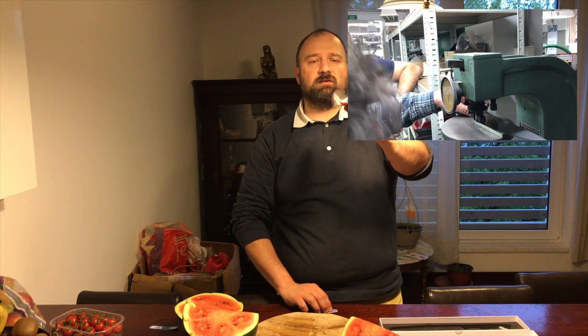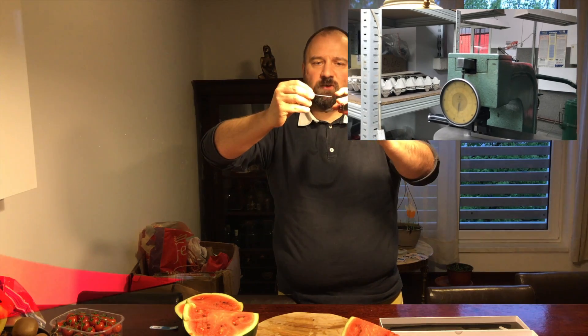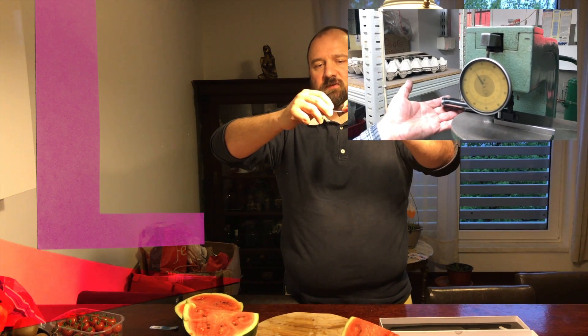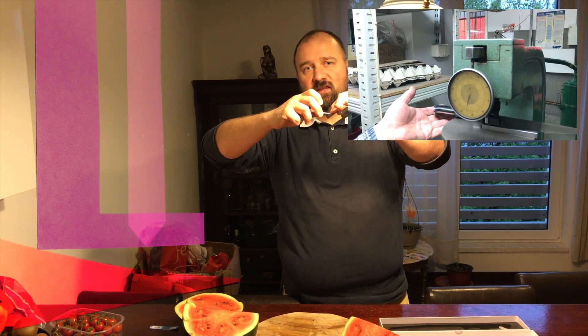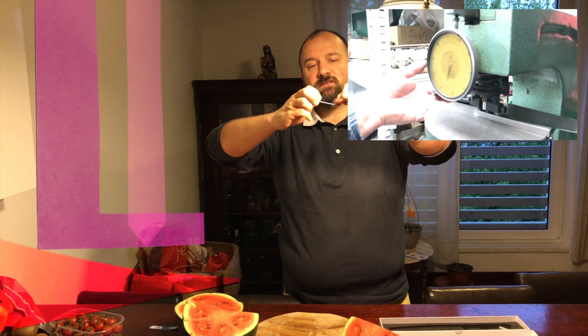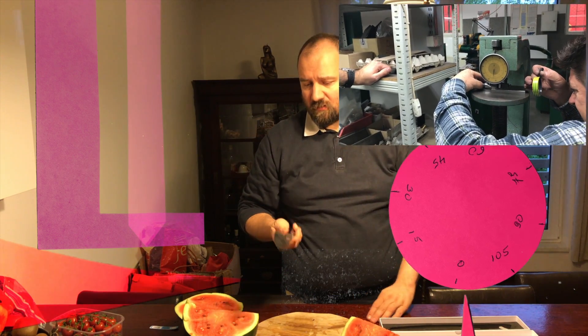The problem is, if you look at the blade, it has a bevel. The hardness machine has a special foot which presses down on the edge. Since the blade is coming down like this, you have a foot resting here, and then there's a hardened tip which presses into the material. The hardness is determined by how much this cone presses into the metal. So if the foot is resting on a sloped surface, it already has some distance and will travel without pressing into the material, meaning the readout is less than the actual hardness.